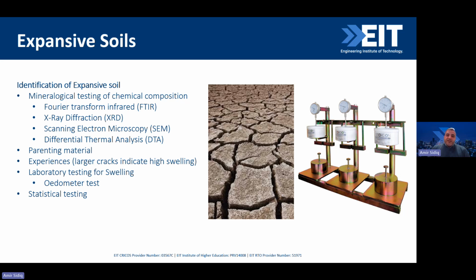We also do some other testing regarding these criteria, where we use an oedometer test. Basically, we try to find the swelling. What is the swelling range? Whether the swelling value is within this particular range, and then you understand whether it's expansive or non-expansive. In some other cases, we have statistical testing. It involves a range of data, and then we do some statistical testing to understand whether this clay is expansive or not. So this is the general idea if you want to prove scientifically that this clay is an expansive clay.